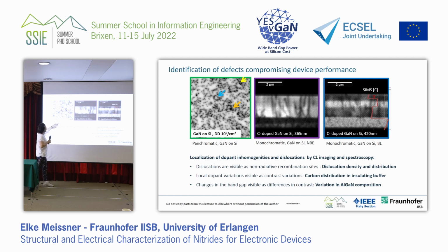So it was a gallium nitride on silicon HEMT, 10 to the 9 dislocations per centimeter squared. You see the panchromatic CL image. You see all these dislocations here. You see that there are clusters, that there can be arrangements of atoms and areas where there is nothing. You see the sequence. This is a step-graded carbon step-doped sample. So you see that this has different carbon content. We did this for calibration purposes of the blue emission line. And we see that dislocations are visible as non-radiative recombination centers. You see all these lines are dislocations here.